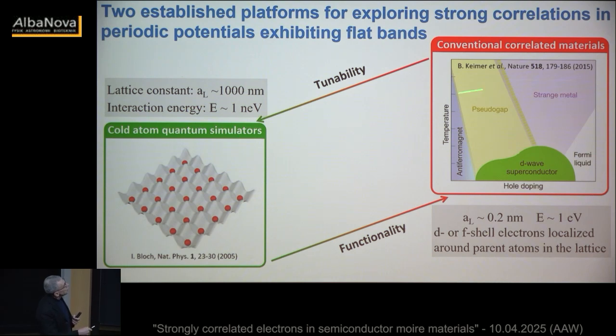Okay? Now, if you compare these two systems, they cannot be more different. If I look at the length scales, for real solids, the lattice length scale is like 2 to 3 angstroms, and the relevant energy scales are on the order of electron volts. For cold atoms, the lattice length scale is determined by the optical wavelength, about a micron, and the interaction energy scales are about a nano electron volt. So for this to work, of course, you have to cool down the atoms to basically nanokelvin temperatures in order to see the quantum effects, where temperature is less than the interaction energy. Okay? So what this system offers is extreme tunability.